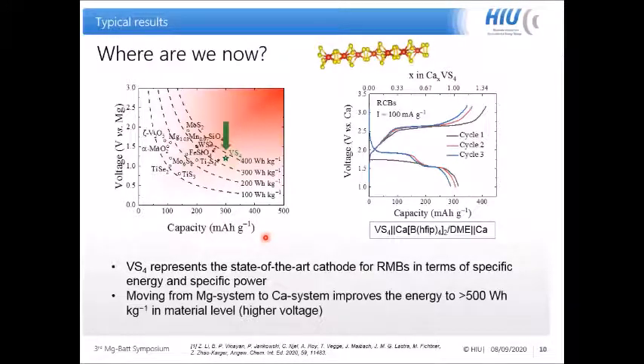We also learned that a further increase in specific energy is possible if we change the magnesium anode to a calcium anode, because calcium is also a divalent metal anode, and the respective cell could deliver a specific energy of 500 watt-hours per kilogram at the material level. This is simply because we have a much higher voltage than in the case of magnesium. The demonstration of these calcium batteries also indicates that the strategies we have applied here could be valid for other divalent ion storage or even multivalent ion storage, which is quite promising.